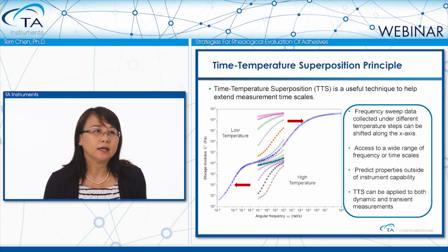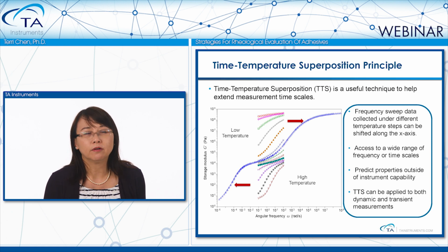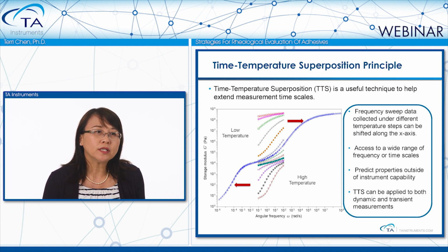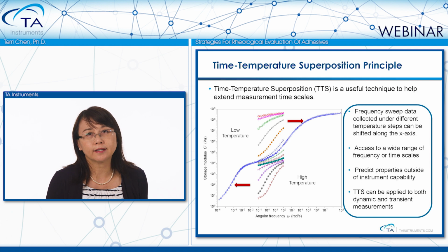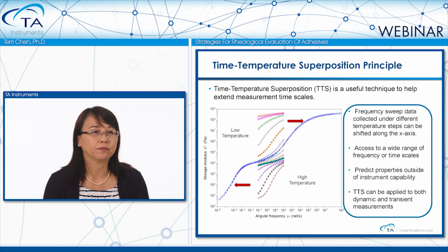Time-temperature superposition is a very useful theory. It is based on the observation that for a thermorheologically simple material, the viscoelastic properties generated at different temperatures are equivalent to the properties measured over broad time or frequency scales. For example, in a dynamic testing, frequency sweep data collected under different temperature steps can be horizontally shifted along the x-axis, which is the frequency.